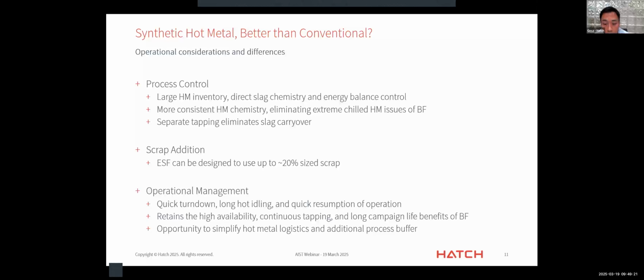I think the mass and energy balance control of the ESF is much easier than the blast furnace, which is usually limited by the burden recipe and fuel rate control, and often comes with significant emission impacts and so on. The separate tapping of metal and slag in the ESF also eliminates slag carryover. That's an additional benefit, of course.